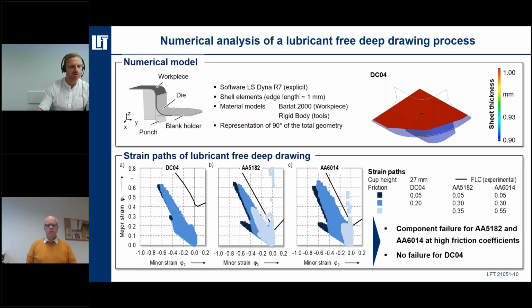Besides these material input parameters, the integration of different friction coefficients is necessary to analyze the different forming behavior. In this regard, different friction values, which you can see here in the blue colors, were set up for different material combinations in order to analyze the forming limit curves of the rectangular cup without material failure. The results reveal that DC04 works for all friction coefficients set up to 0.2. However, aluminum will fail with friction coefficients above 0.3. The black lines are crossed, which you can see here, which show that material failure in terms of crackings are expected. It also can be seen that aluminum alloy AA5182 has an improved forming behavior compared to aluminum alloy AA6014.